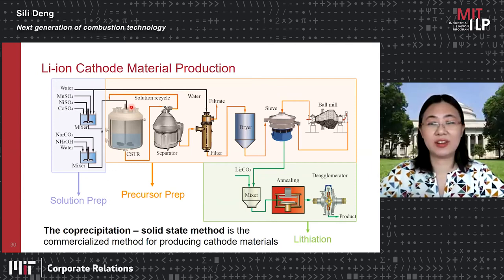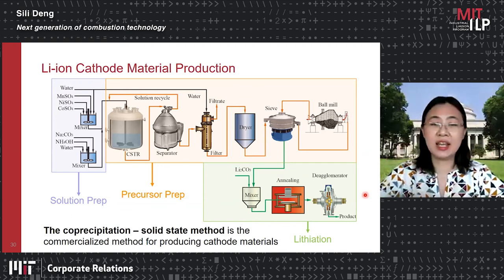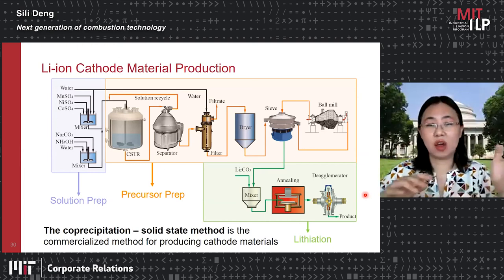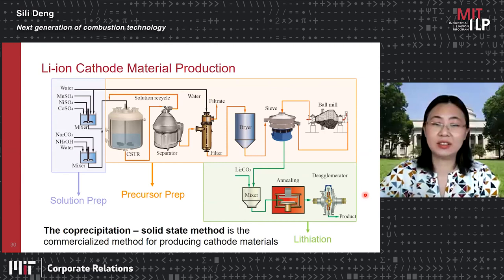It's a very complicated process. And then during this lithiation process, you mix this transition metal oxide with the lithium carbonate. And then you can formulate this lithium ion cathode. Then the inhomogeneity and the phase separation will be a big problem. And also you can see this whole process is very complicated.